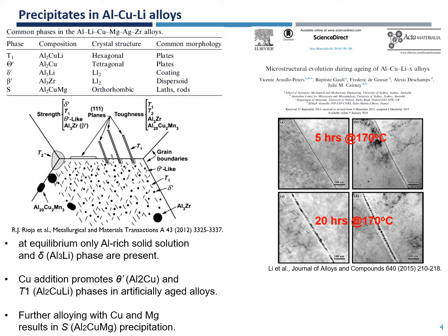The main strengthening phases of aluminum-copper-lithium alloys are the T1, delta, and S phase. The T1, with a composition of Al2CuLi and a hexagonal crystal structure, is more often present after the artificial aging of these alloys, as can be seen in the right figure, and usually on the grain boundaries as well as in the interior of the grains.